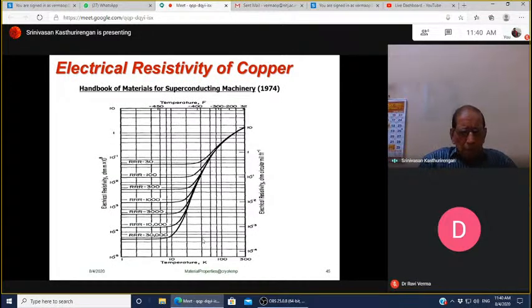Now, the electrical resistivity of copper is plotted in this graph. It is in ohm meter into 10 to the power minus 8, I think, if I am not wrong, plotted on the y-axis, and on the x-axis is the temperature. So for different RRR values of copper, you see 30, 100, 300, 1000, and then 3000, etc. These are from the Handbook of Materials for Superconducting Machinery in 1974. We have taken this data from this data book. So you see, as you go on increasing the RRR values, the residual resistance value is very small, so the electrical resistivity completely drops.